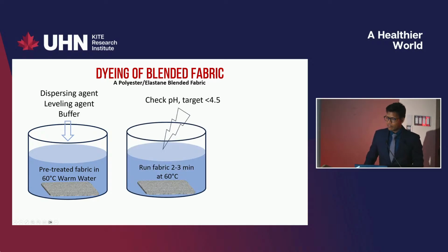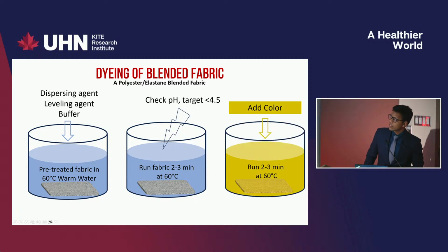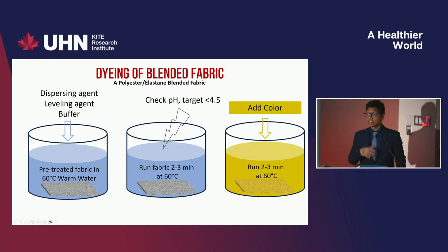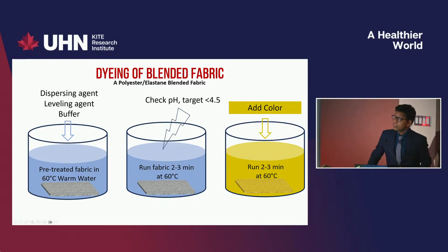Then we try to run the fabric for a few minutes, here in this case 2-3 minutes, and then we check the pH. We keep adding the buffer solution until we get the pH in an acidic range, less than 4.5. After we get the pH in an acidic range, we add color. For instance, here for this fabric, for example, I'm aiming for a yellow color. It was less attractive. I don't know why I picked that, but we can start with the yellow color. So we try to run the fabric in the similar temperature at 60 degrees centigrade temperature.